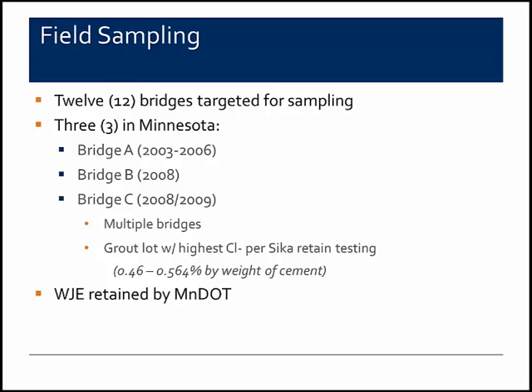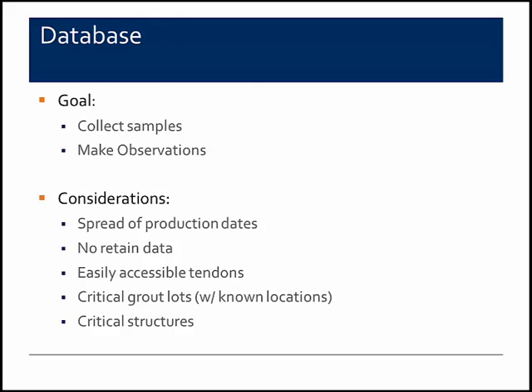And the Bridge C project is actually a collection of multiple bridges, one of which was known to contain the grout lot with the highest known chloride content per Sika's retained testing. It was 0.56% by weight of cement. And WJE was fortunate enough to be retained by MnDOT to participate in some of the field sampling in Minnesota.